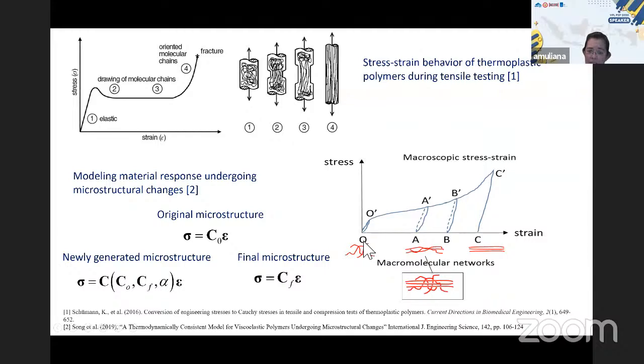One thing I also try to point out here, when we look at the microstructural changes: when you load this and at some point there is a microstructural change, and you unload, you see this area that is associated with energy being dissipated. So when there is a microstructural change, there is energy being dissipated. In addition, polymers undergo viscoelastic behavior, so there is a delayed response. So in addition to all these microstructural changes, there is also energy dissipation due to the viscous, or viscoelastic, effect of this material.